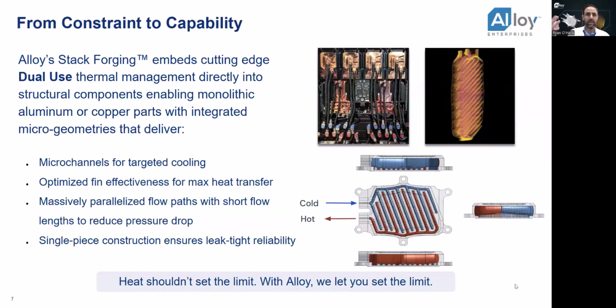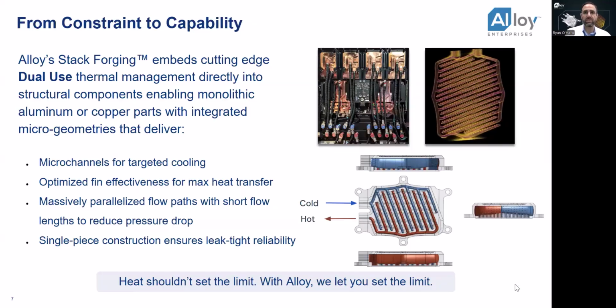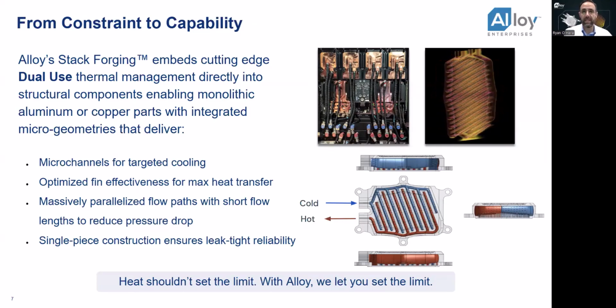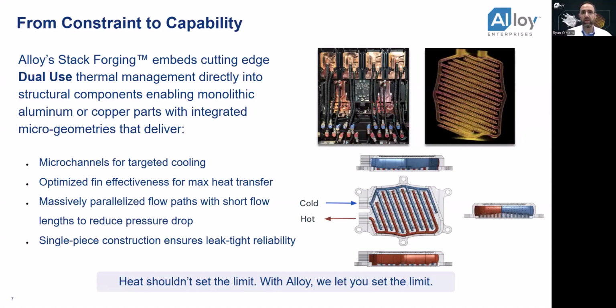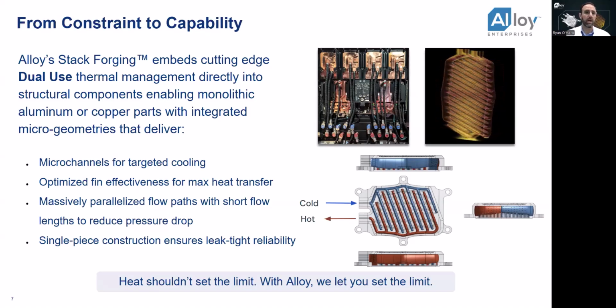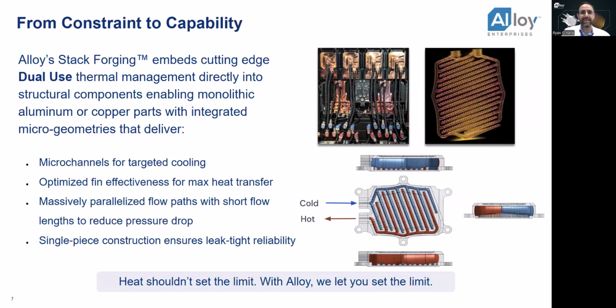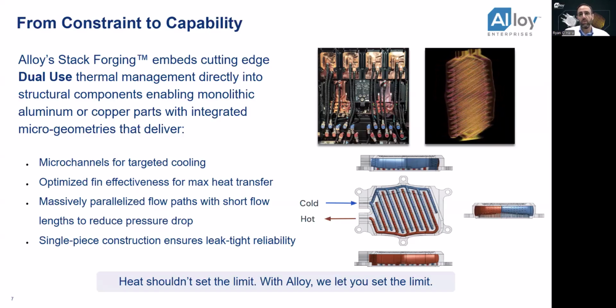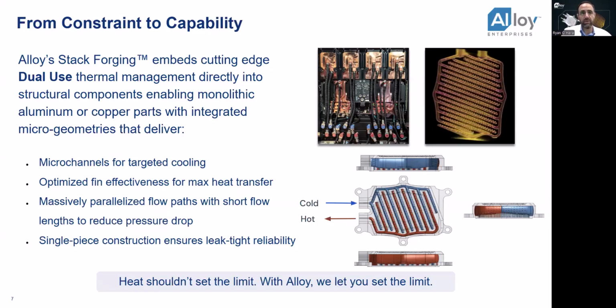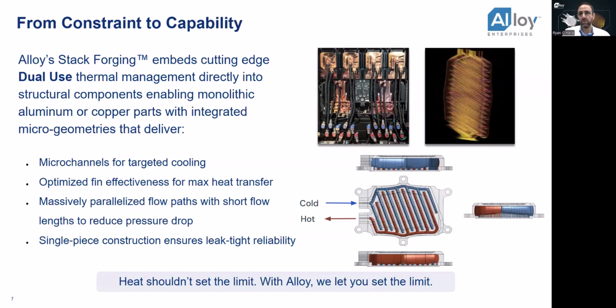So stack forging allows us to embed thermal management features that conventional manufacturing simply can't achieve. What you see here are examples of microgeometries we can build directly into monolithic aluminum and copper blocks. We have microchannels, which give us precise targeted cooling exactly at the heat source. We have optimized fins and geometries, which increase surface area for maximum heat transfer, something you just can't get with traditional brazed plates or other manufacturing methods.